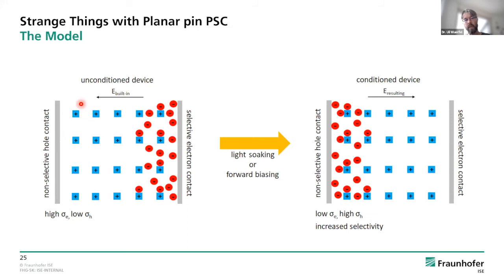Now, of course, you can easily think that because here we have excess positive charge, holes will be repelled from that region and electrons will be attracted. So what we get here close to this hole contact, due to the distribution of the ionic species, is a rather high concentration of electrons and therefore a high electrical conductivity of electrons. It's proportional to each other. And at the same time, a rather low hole conductivity, because holes are repelled by this positive charge here.